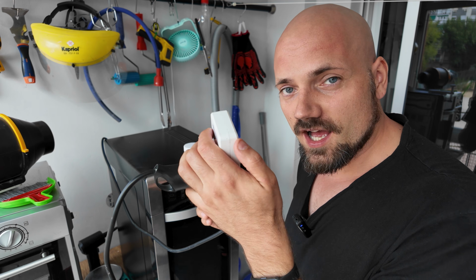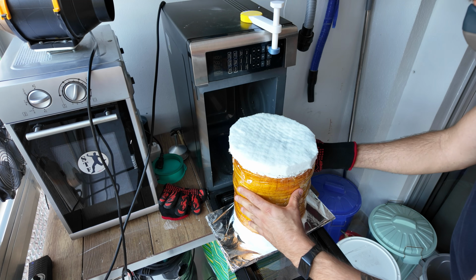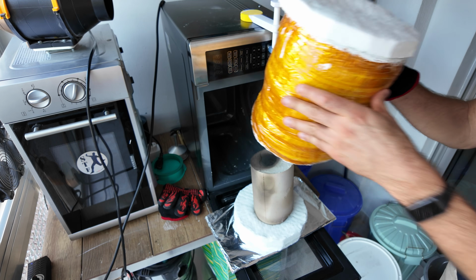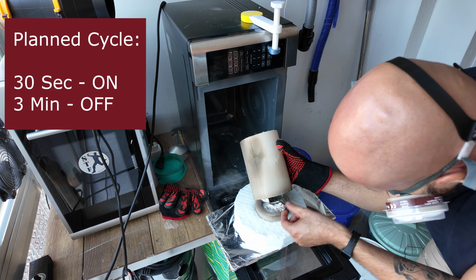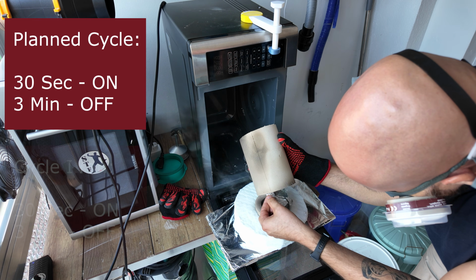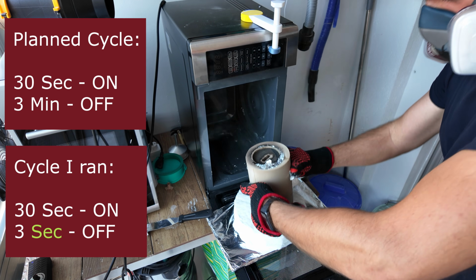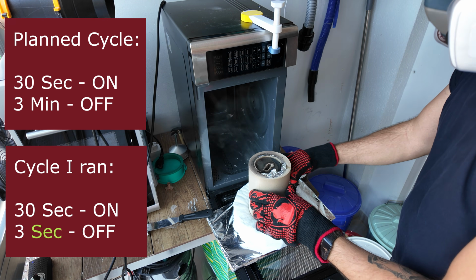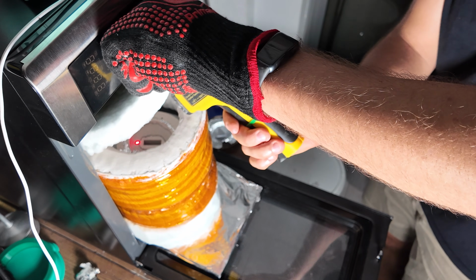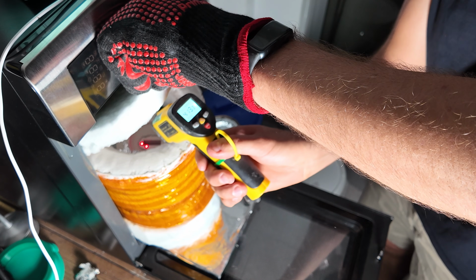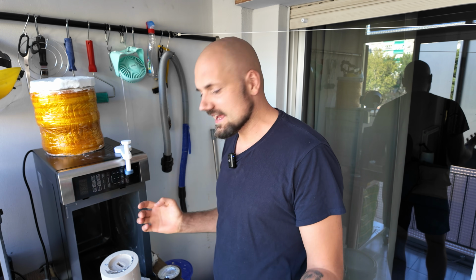I just need to adjust my cycle. I accidentally set my cycle timer wrong. Instead of the microwave staying off for 3 minutes, it was off for 3 seconds. In other words, I started the burnout super aggressively. Well, the good thing is that we did burn out the mold.